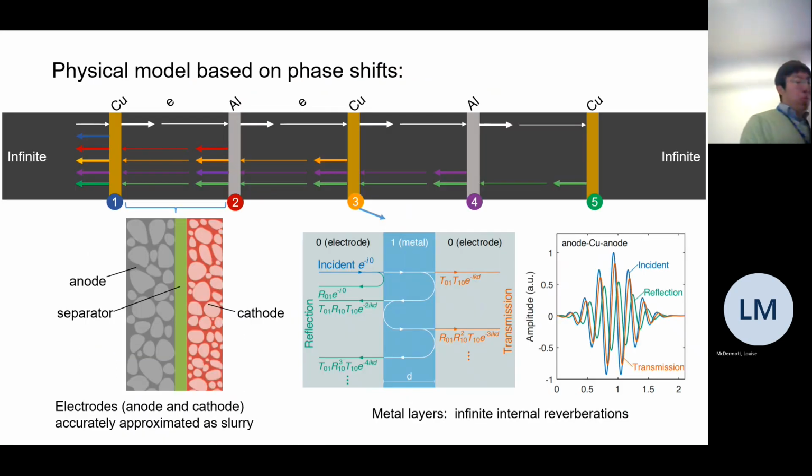So we established from the ground up a wave physics model in order to explain the resonance. You have these metal current connectors inside of the battery, which are the main reflectors of ultrasonic propagation, which goes in this direction.